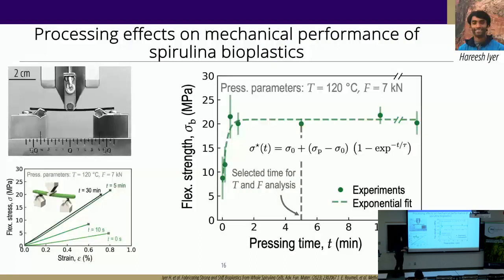We want to see what are the changes that we can induce to this powder, basically. So we're going to be doing 3-point bending tests for this particular experiment. You see different curves over here, just force displacement, stress strain curves. And then you see the extracted strength versus time. So it's a 1D slice where we're keeping the temperature and pressure, and we're only seeing the effects of time. And we're seeing how the different pressing time is influencing the strength of the beams that we are able to produce. And you see an exponential type of behavior.